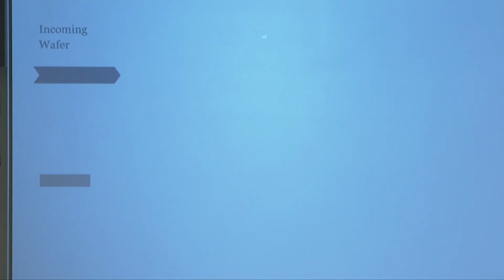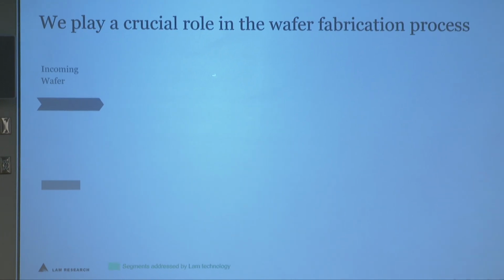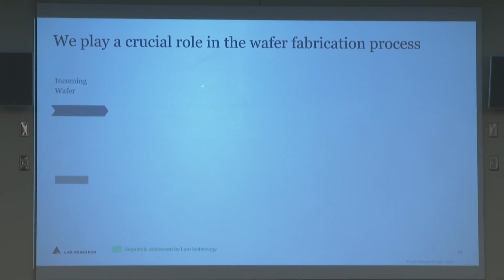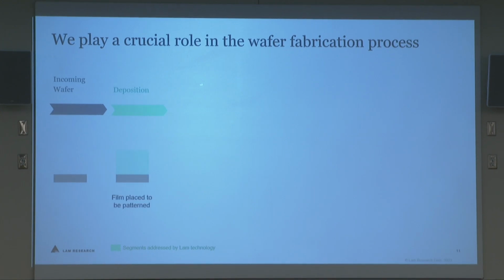So the role that Lam plays in wafer fabrication, this is a really rough schematic. If that gray bar at the bottom is a silicon wafer, and most of the industry is 300 millimeters right now, so 12 inches, it's like the size of a large pizza. You can think of that as the size of the wafers. We do a lot of deposition of thin films. Roughly, you deposit a film, and chips are ultimately 3-dimensional structures, so that has to be patterned. So it'll go through extreme UV exposure, which is currently the industry standard. It can print down to, let's say, around 10 to 13 nanometers.